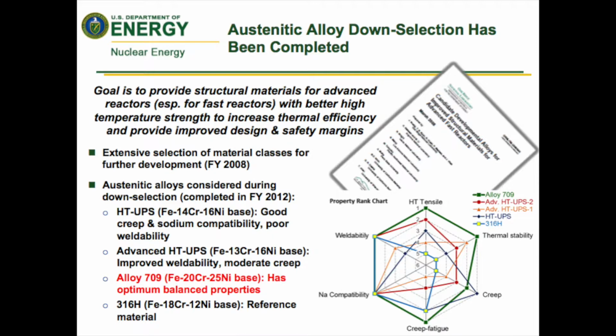The materials that we started looking at, if you look down in the lower right corner where I'm pointing with the pointer, you can see some of the materials we've been looking at. The advanced high temperature ultrafine precipitate strengthened materials, alloy 709, I'll talk about that extensively, as compared to the 316 stainless steel, which is the base material that is currently in the ASME code. And if you look at this blue shaped space on this radar chart, you can see the kind of properties, particularly high temperature strength and creep, that we were looking at as baseline materials, and we're trying to improve on that.